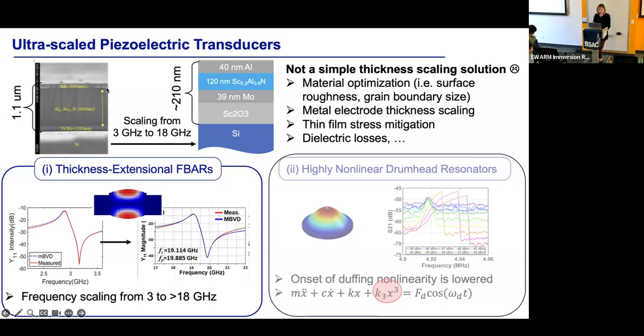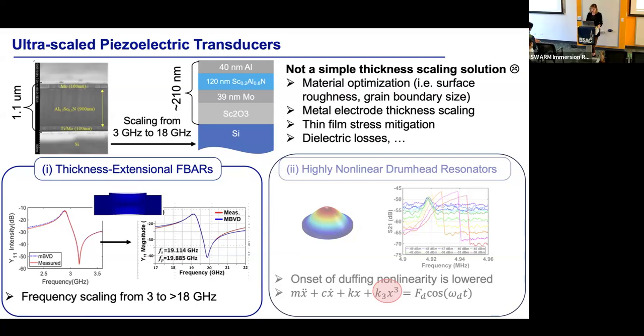So we're going from a film that is about 1.1 to 1.2 microns to a piezo stack that is about 200 nanometers thick, right? So this is not a simple thickness scaling solution. There's a lot that happens when these thicknesses are scaled down. The wavelengths become comparable in size to all these non-idealities in your material, such as the surface roughness, and the size of the grain boundaries becomes important. And then you also have to thin down the metal layers, right? Not just the piezo layer. So how do we thin down our metals without increasing the sheet resistance? And how do we deal with stress and breaking of the devices, power handling, dielectric losses, and so on and so forth?